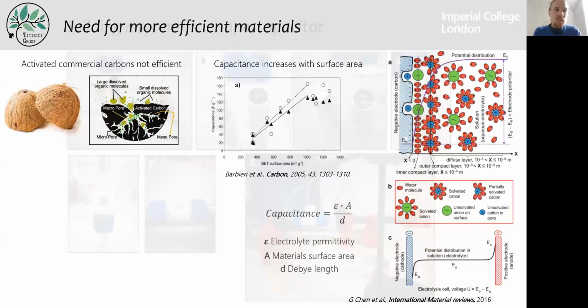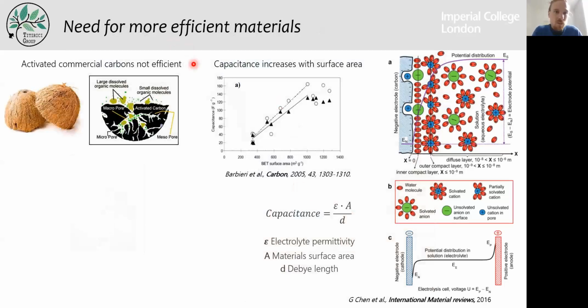So why do we need more efficient carbon materials? That's a good question. At the moment, the commercial carbons are produced from coconut shells because they contain a lot of lignin, and lignin has a high carbon yield. When they steam activate these coconut shells, they obtain hierarchical carbon structures with meso, macro, and micropores. The problem is that these structures are not really efficient for charge storage in supercapacitors.